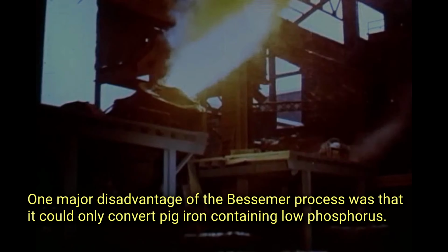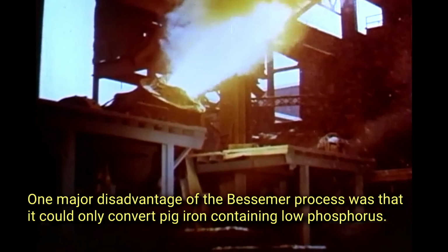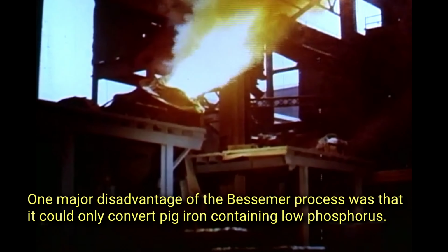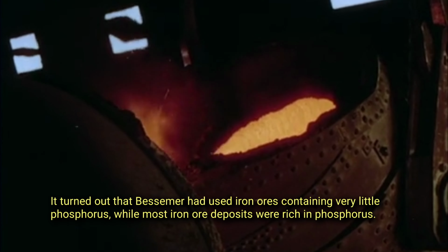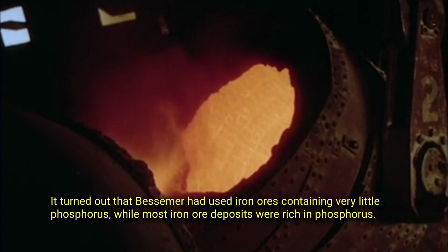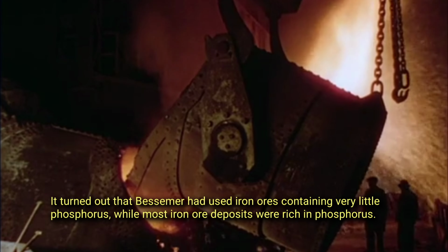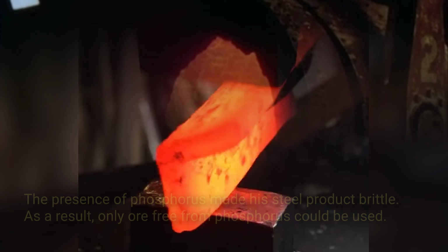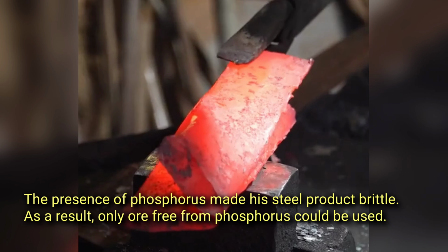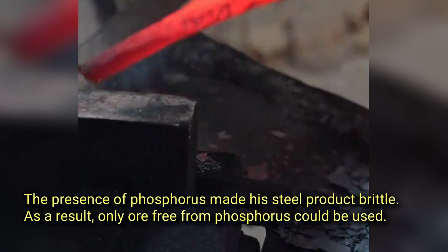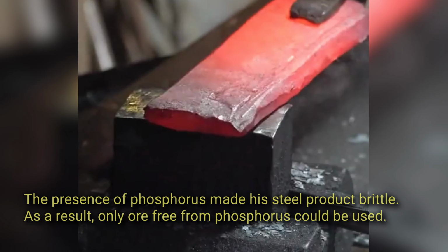One major disadvantage of the Bessemer process was that it could only convert pig iron containing low phosphorus. It turned out that Bessemer had used iron ores containing very little phosphorus, while most iron ore deposits were rich in phosphorus. The presence of phosphorus made his steel product brittle. As a result, only ores free from phosphorus could be used.